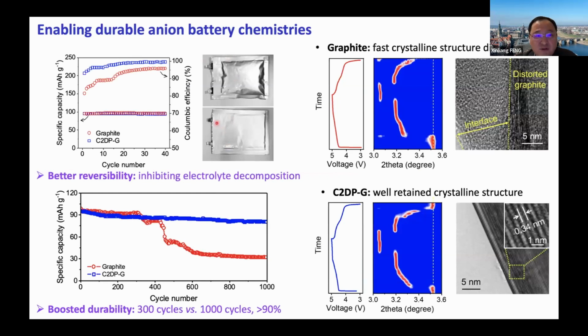Then we examine and make the pouch-cell failure device. So this is our device. We look at the specific capacity and also the Coulombic efficiency. Without the membrane, they do not sacrifice capacity; they have very comparable capacity, and the Coulombic efficiency is very much enhanced with the protection of the membrane. Without the membrane, it's only about 90% up to 40 cycles, but with the membrane protection, they are very stable. This can be reflected in the failure device. With the protection membrane, it's very stable. Without the membrane protection, it shows swelling because of electrolyte decomposition.